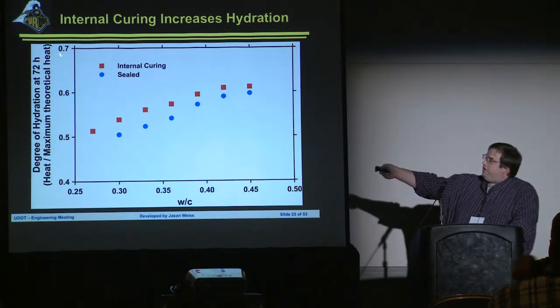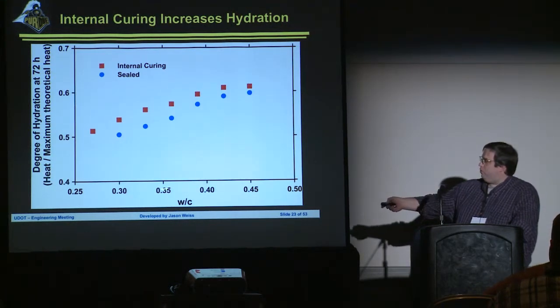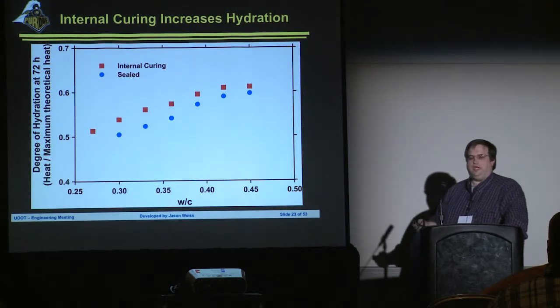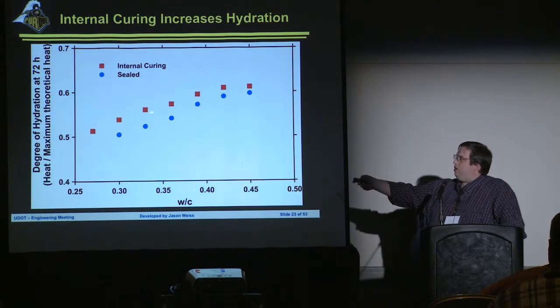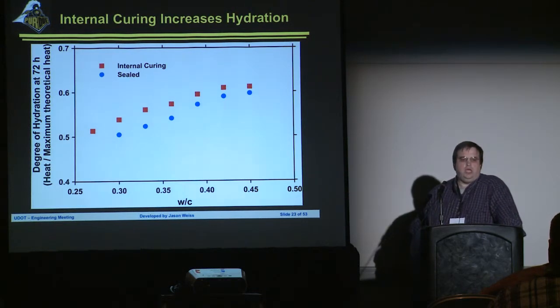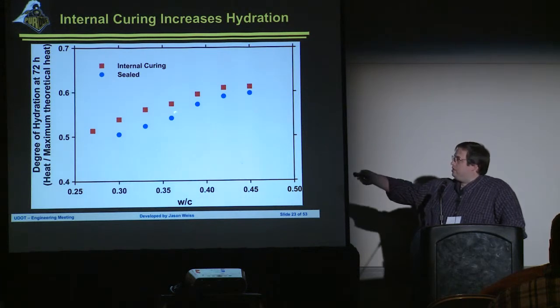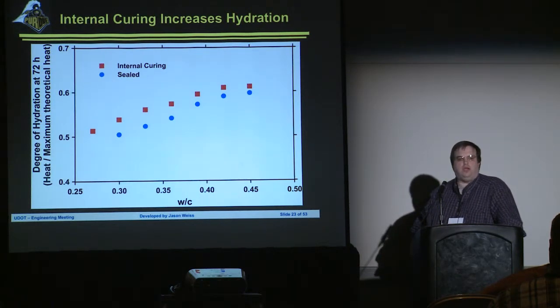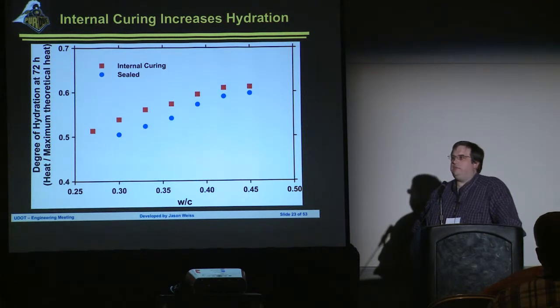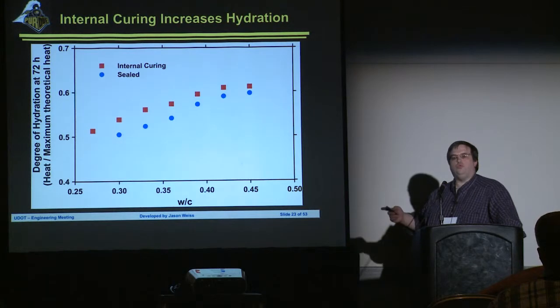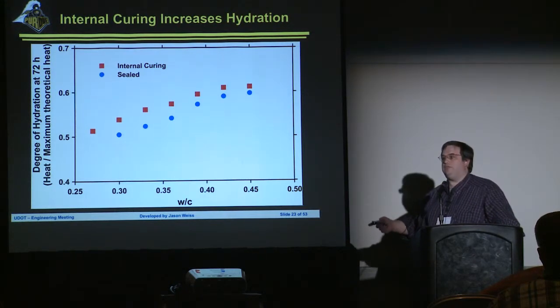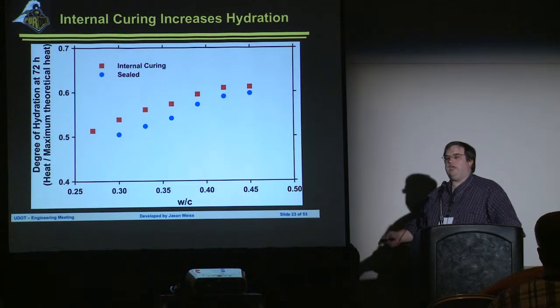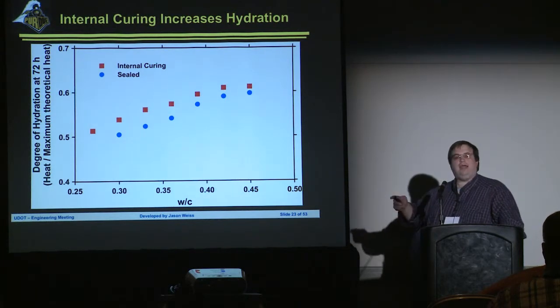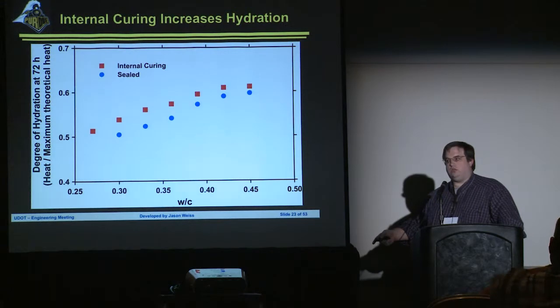This is the amount of heat that's been released by a cement paste with different water to cement ratios after 3 days. Right? These dots are internally cured mix. These blue dots are essentially a conventional concrete. And what you can see here is more heat is being released when you've got internal curing. And I can already see a couple eyes going, big whoop, more heat was released. How does that help us? Well, heat release is a direct measure of how much cement has reacted. So what we're essentially saying is, at 3 days, we've reacted more cement in the internally cured system.